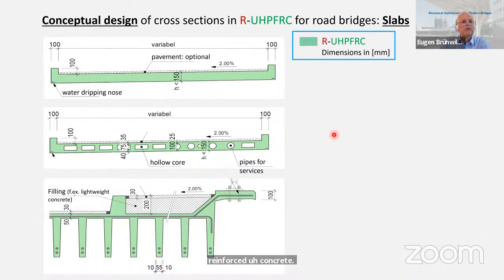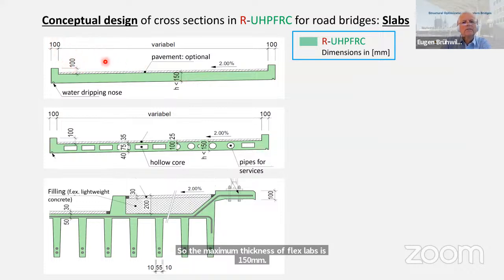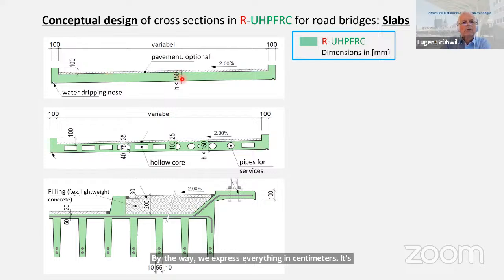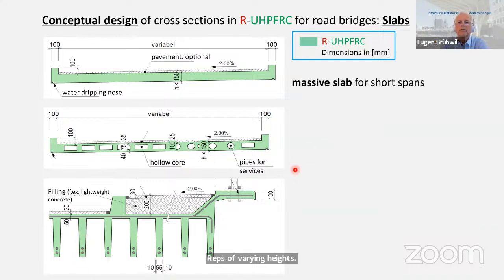Here are some sketches of the conceptual design principles for flat slabs. So the maximum thickness of flat slabs is 150 millimeters. By the way, we express everything in millimeters, not in centimeters. It's like in steel construction. I would say 150 millimeters is already very thick. The thickness is such that actually we can put hollow cores into such a cross-section, pipes for services, and so on. So we are mostly looking at thin slabs and ribs. Ribs of varying heights, integrating rebars.